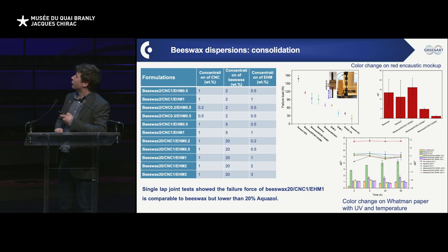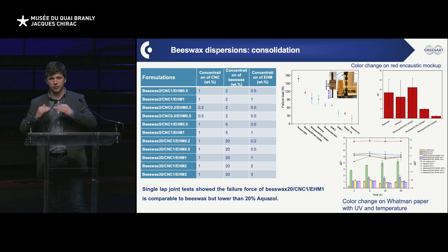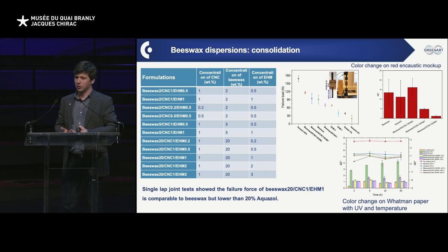If we look here, we have the pure beeswax. Essentially here we have the Aquazol. So the delta E star is much higher. This is our most concentrated 20% of beeswax, but if we start diluting the amount of beeswax, we can really recover and be nearly invisible or much less visible in terms of appearance. So we were pretty happy with that. And of course, if we keep diluting, we can get something that is very, very light in terms of appearance.